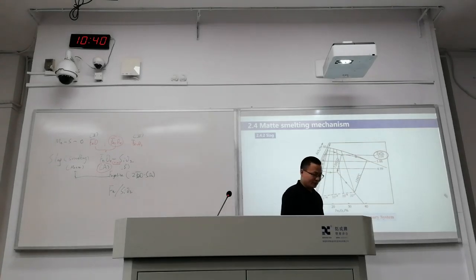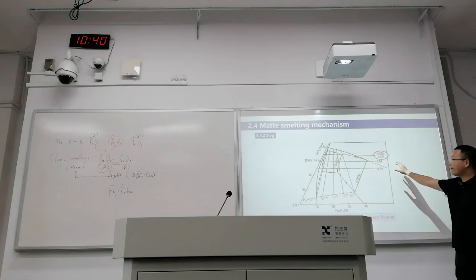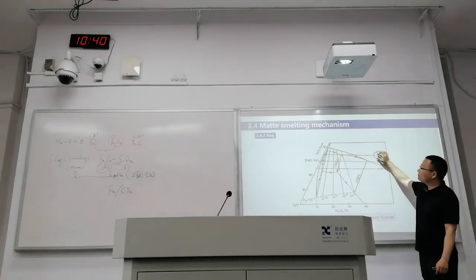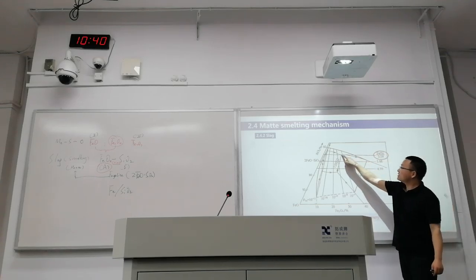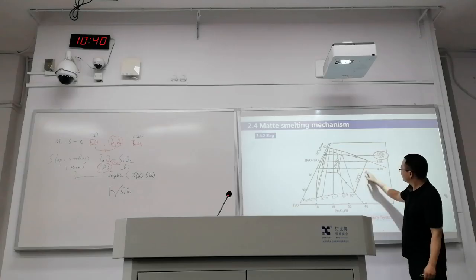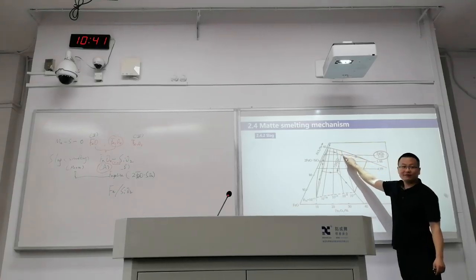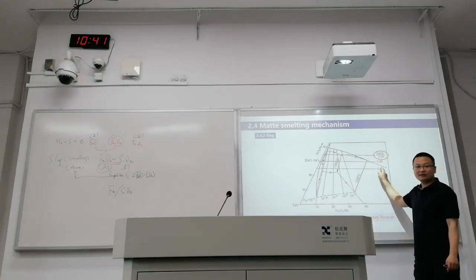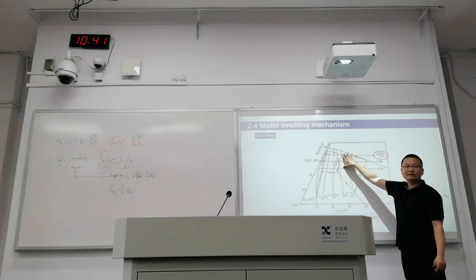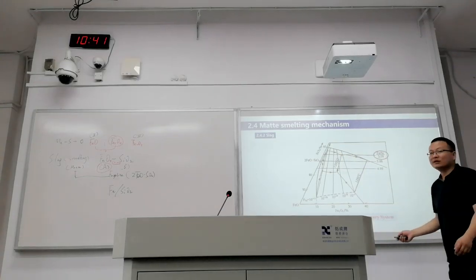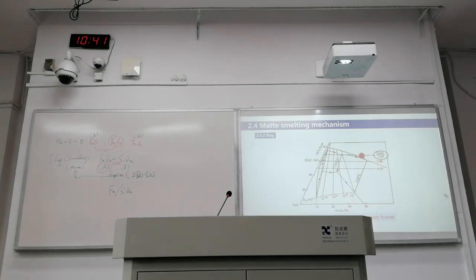Yes, big regions. But as we have already mentioned, if we are having a small iron silica ratio, this is the liquidus, so this is the boundary line, right? Actually, this is the liquidus for 1300, so we have a very small region here. But if we have a big iron silica ratio, we have a bigger one, right? So this is something we are discussing. So iron silica ratio, temperature, and oxygen potential are the most important parameters for slag. You are writing right on your slides: oxygen potential, temperature, and composition. They are the most important properties or information about our slag.